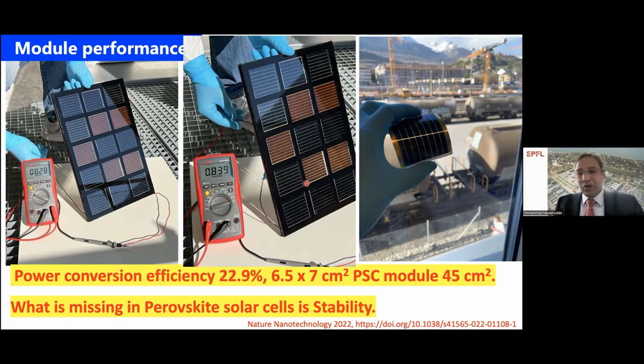At the same time, we can also develop flexible perovskite solar cells. Efficiencies are slightly lower than on the glass substrate, but it is possible to get high efficiency. So the take-home message from these few slides is the power conversion efficiency of these mini modules. We have reached over 22% efficiency. The size is shown here, 6.5 by 7 centimeters, resulting in 45 square centimeters.